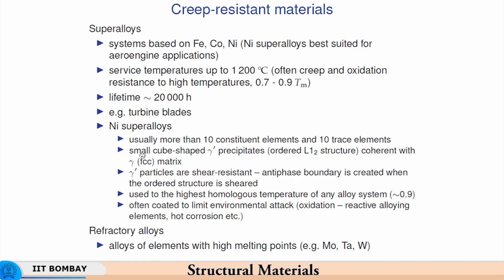So, typically in nickel based superalloys there are about 10 constituent elements and 10 trace elements. Now, trace elements are the ones which are added or which are there, not necessarily added. So, trace elements would mean that either there are impurities which could not be removed, and therefore, the traces of impurities remain behind, or certain elements which are added as trace to control the diffusion rates. So, the precipitates which form or the intermetallic particles that form could be aimed at reducing the dislocation movement inside the grains.